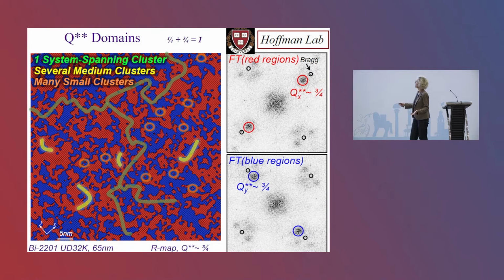So this red cluster, actually, you can walk from one side of this sample, of this field of view, to the other by making nearest neighbor steps onto red pixels. And so there's one large connected cluster. There are several medium clusters. I've highlighted those in yellow here. So the blue clusters are medium scale clusters. And there are many more tiny clusters. So I've circled some of the red clusters that are tiny.